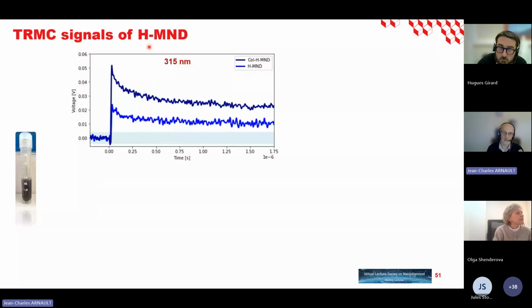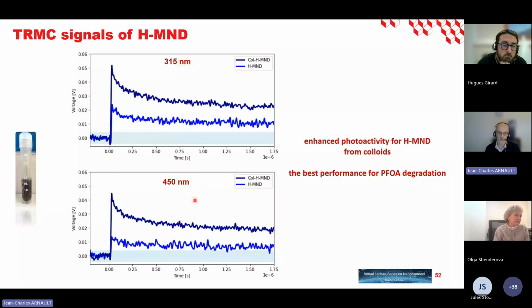And then for the hydrogenated particles, we compare the particles you have seen before, extracted from the hydrogenated powder, with the ones that were in suspension, then dried and measured. And as you can see in the UV range, we have a very significant difference in terms of photoactivity. What about the visible range?